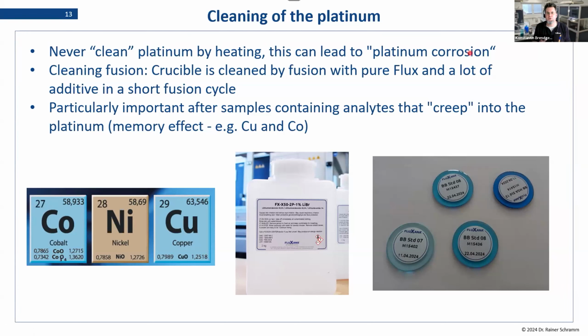In case you want to do an extra thorough cleaning or an extra high intensity cleaning, what we always do is what we call a cleaning fusion. That means we take our tetraborate, our flux, usually the one that we use for samples as well, and we add a bit of additive into there so that it flows more easily. And then we just do a blank fusion. So we make a cleaning program on one of our machines, for example, and we only put flux and a bit of additive. And then we make a quick run and throw away the bead. But that helps a lot with cleaning out the platinum ware after difficult samples.